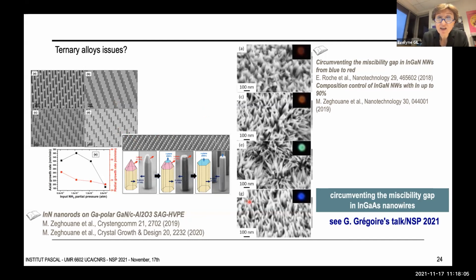And it is also possible to circumvent the miscibility gap in indium gallium nitride nanowires, here grown by VLS. And that was demonstrated by our group and the group of Peidong Yang in the USA. And in the case of VLS HVPE, we suppose that this is due to pure atomistic growth that does not need macroscopic nucleation. I mean, that doesn't need to have the formation of a reservoir, so it avoids the reservoir effect.